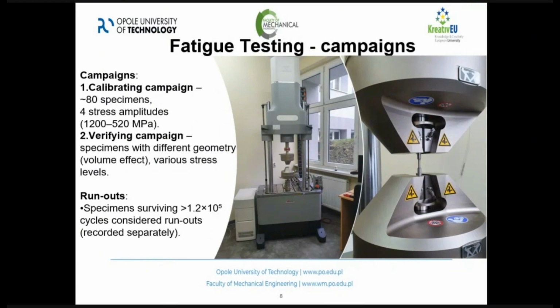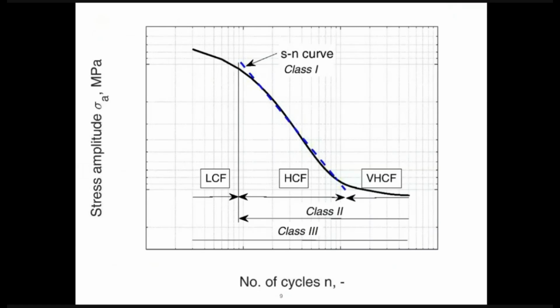And then we did a verifying campaign with a different specimen size. I mean, the shape was close enough, but the specimen was a little bit bigger. It will be shown later. And also some of the specimens were runouts, and we decided that the runout will be 1.2 times 10 to the 5th, so 120,000 cycles.